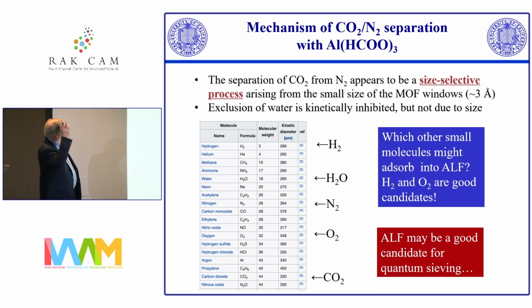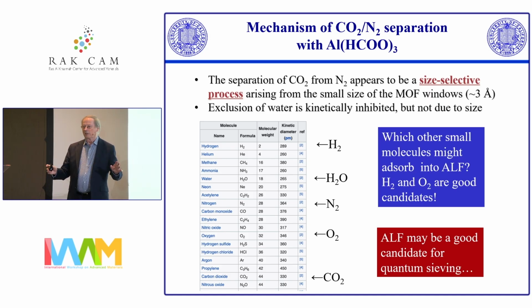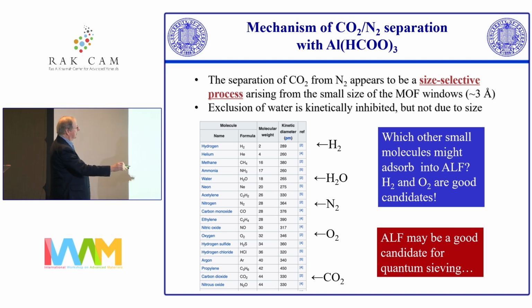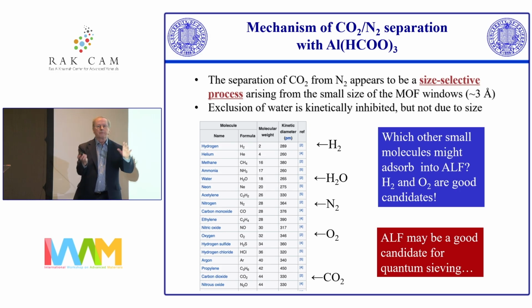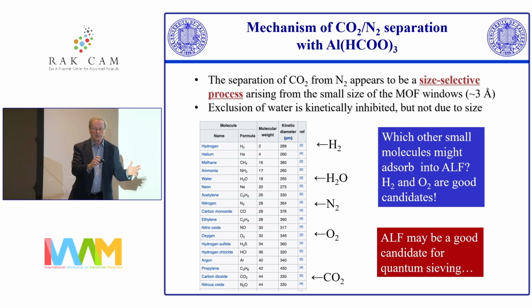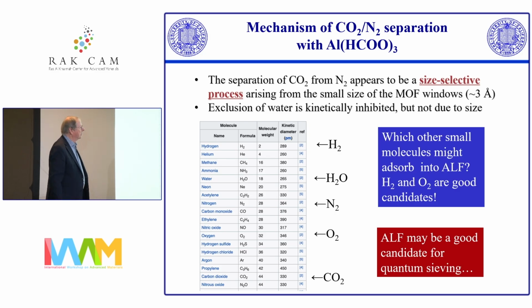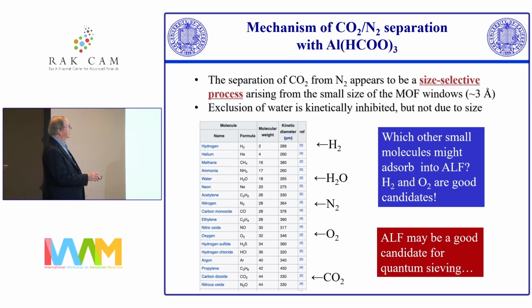So initially, when I made this slide, I really believed it. I thought it was size selective because we could separate CO2 from nitrogen, and nitrogen is bigger than CO2. And I thought, we should be able to adsorb oxygen and maybe separate oxygen from the nitrogen in the air. And so that seemed a good thing. And so we've been looking at that.